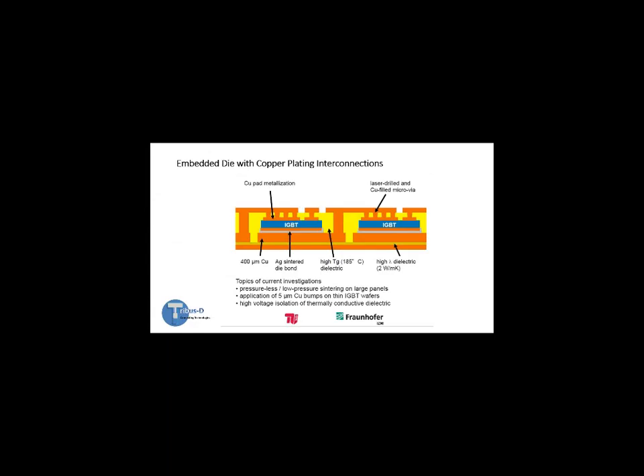And also in the embedded fields, if people have control of the MOSFET, you can put copper metallization onto the MOSFETs at the foundry, and you can then use plated connections within an embedded PCB using laser drilling and copper-filled microvias to form the connections. So there's lots of activity going on in embedded systems, but in this particular case, you've really got to have control of the die which you get from the foundry in order to be able to implement it.